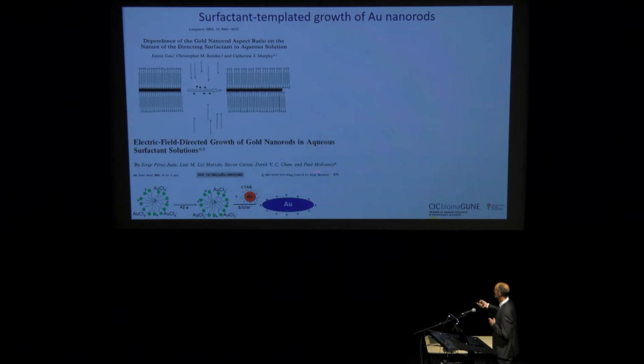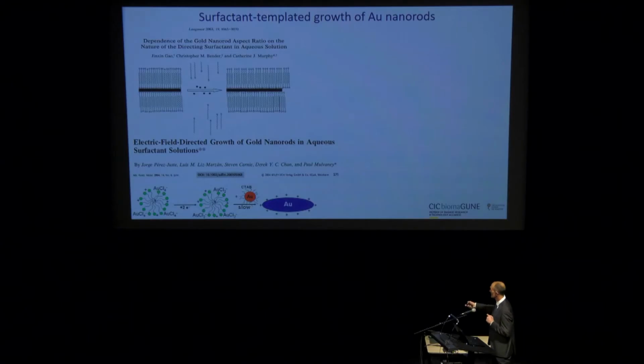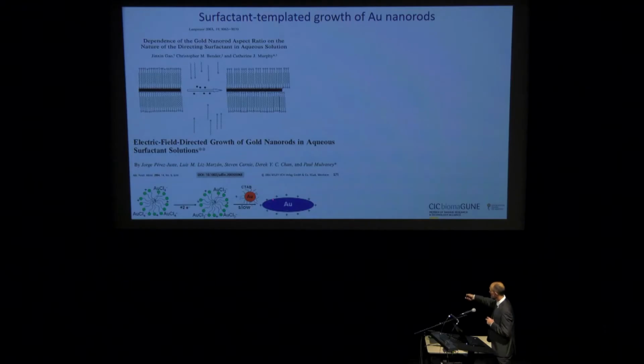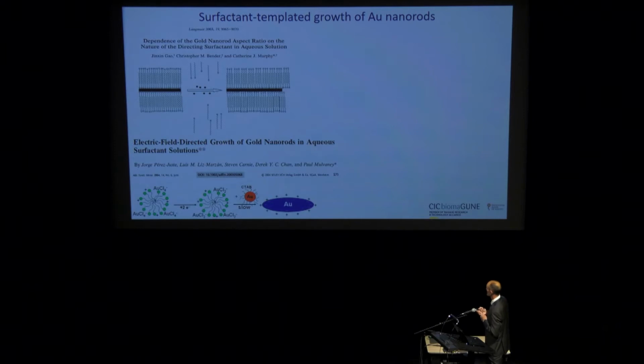Our work together with Paul Mulvaney in Melbourne was actually related to the distribution of the surface potential depending on the elongation and the curvature of the particles. And so the idea was, if after growing spherical particles they become slightly elongated because of symmetry breaking, then the most curved parts of the particles will have a potential that decays much faster, so that the micelles with gold ions will be easier to be reaching these highly curved parts and increase the elongation of the particles. And all of this, I think, still makes sense.